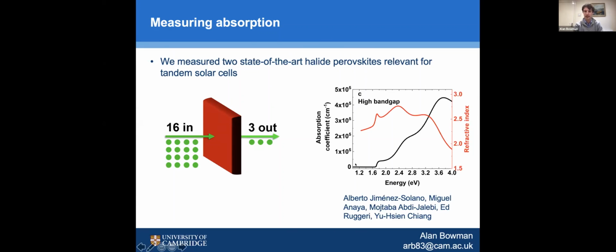But if you look at this black line, basically you absorb no light. And then there's this turn on here. So above about 1.7 electron volts, which in English means red light, for red light upwards, you start to absorb quite a lot of photons. And what this experiment allows me to do is not only work out how much this specific material absorbs, but from that I can then calculate how much different thicknesses of the same material will absorb.